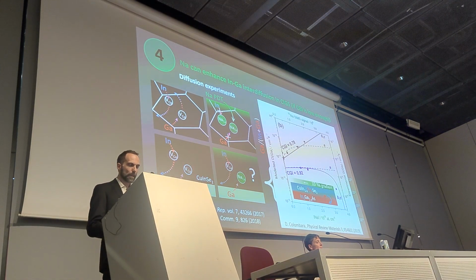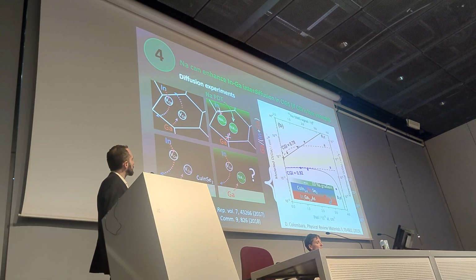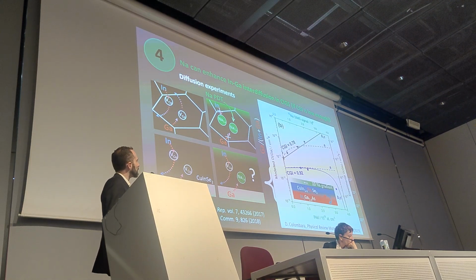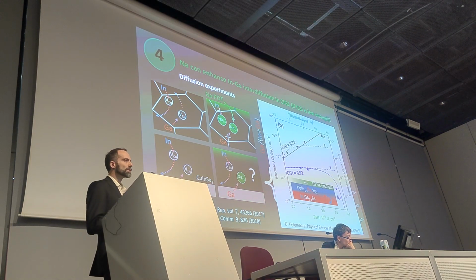If you have a lot of copper vacancies, whenever you add a little bit of sodium, this helps indium and gallium to interdiffuse. But if you add too much sodium, or you don't have enough copper vacancies, then sodium hinders interdiffusion of indium and gallium. In the same, let's say, rationale that was proposed 20 years ago. So sodium effectively can enhance interdiffusion of indium and gallium under certain conditions.